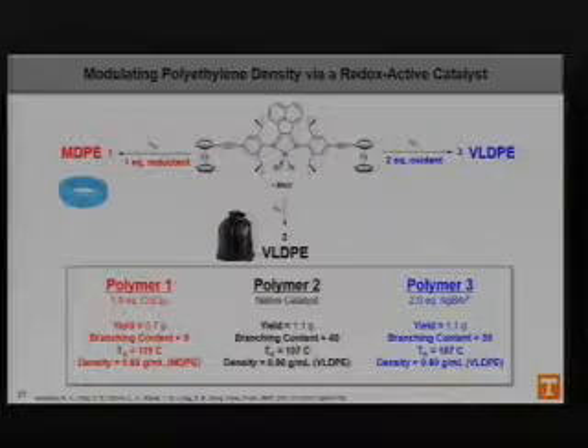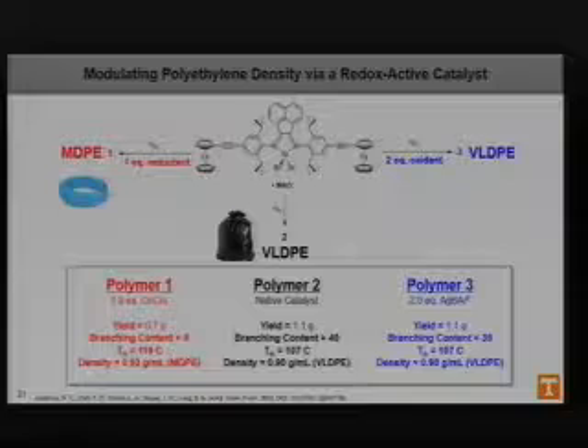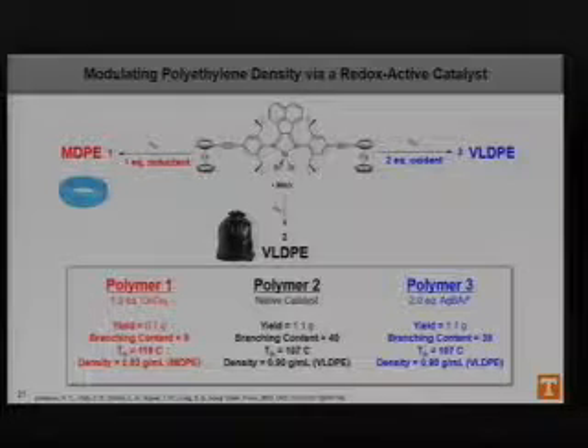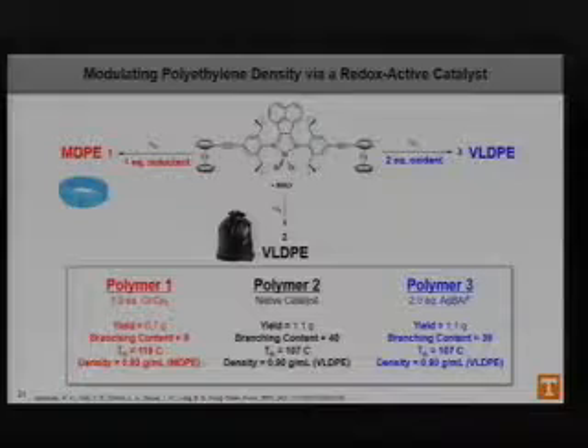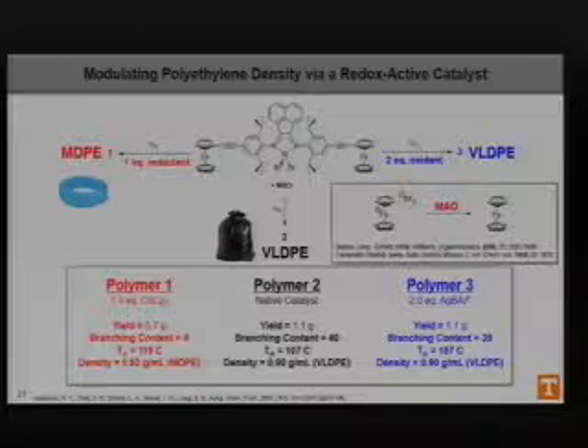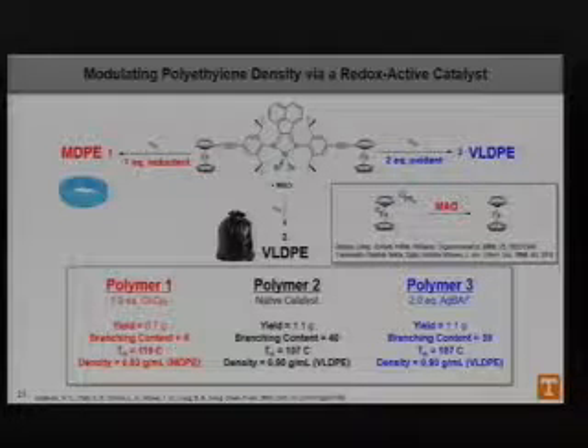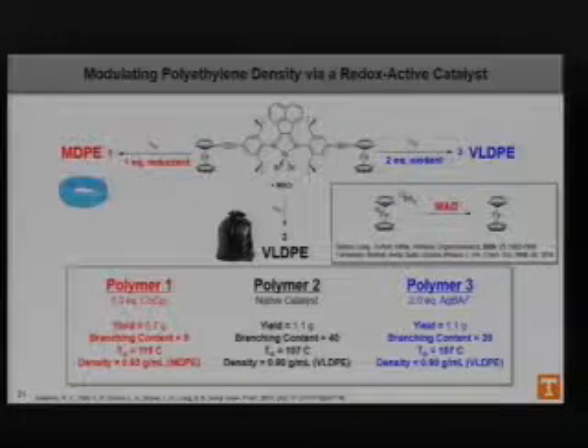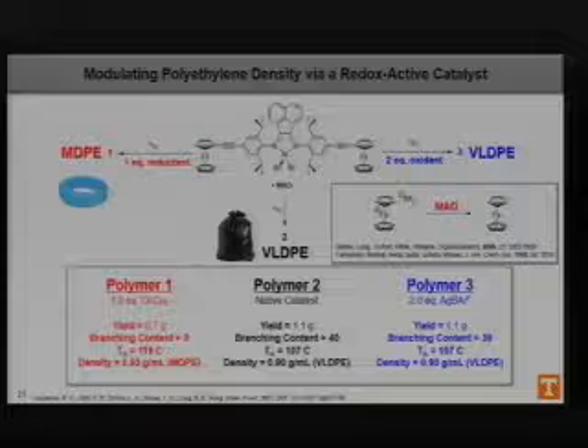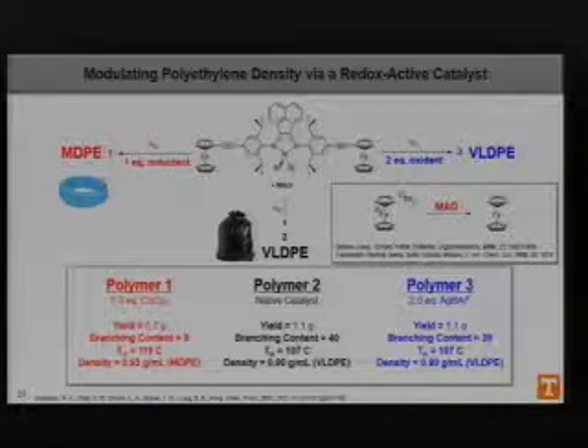Now, when we added in 2 equivalents of oxidant to try and oxidize these ferrocene moieties on the outside, we were not able to get any results that were different from the native species, so it actually didn't work. And we believe that is because the MAO that we have to use as an activator is re-oxidizing the ferrocene back. So that aspect of the project kind of failed. But the other part worked, so that was still pretty exciting.